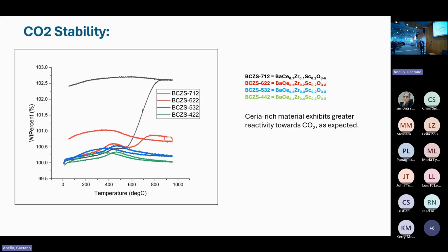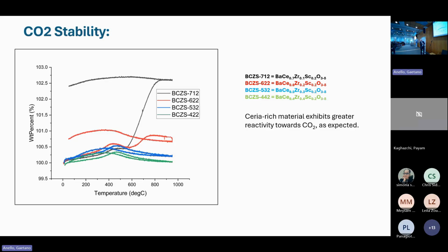It's very simple thermodynamics. If the thermodynamic driving force is to form the carbonate, it will do it. If you replace cerium with zirconium, the thermodynamics become less favorable. Scandium also is a small ion. So you can easily move to the situation like you have with the green and the blue, where there's no uptake of CO2, just a small reversible change.